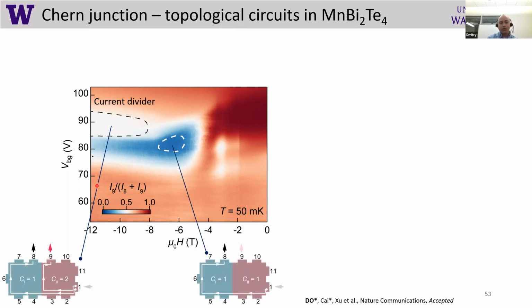So what we can see is the following. In this dashed region, our sample works as a current divider. So essentially we send current and get 2 identical currents on 2 terminals. And it doesn't depend actually on the terminal, but the important thing is the domain. We can also decrease magnetic field and decrease backgate voltage and get to this region where I9 is 0. Now I9 is 0 because there is no edge state going this way. So all current gets from terminal 1 to terminal 8.